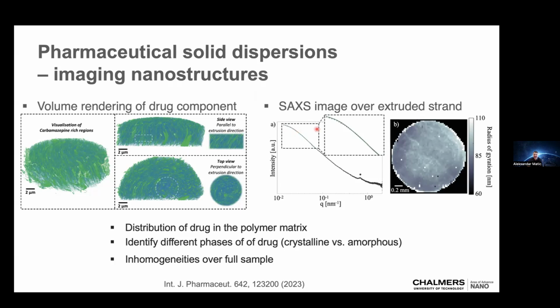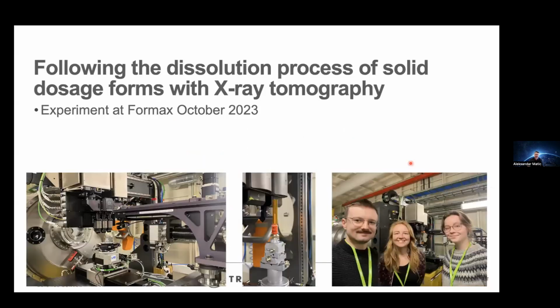So then we did scanning SAXS imaging, where we imaged here, for instance, the low Q region over the whole sample. So the color here would basically represent the radius of gyration of the polymer in this case over a full extruded strand. So a 1 millimeter sample or 1.5 millimeter sample, and you can see that in fact it's quite representative. But then we went instead to ForMAX, because what Martina now wanted to do was to look at formulations in a condition that is similar as when you take a pill, you swallow it, and you have the dissolution taking place inside your body.